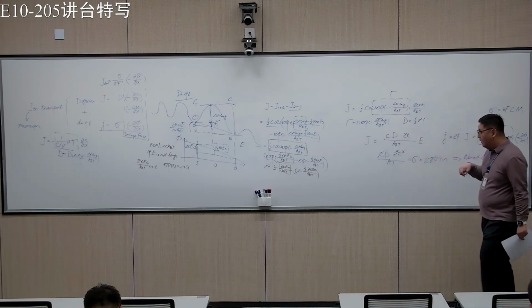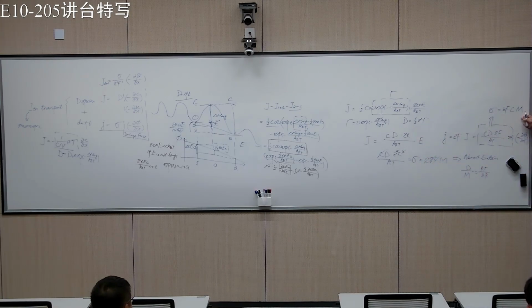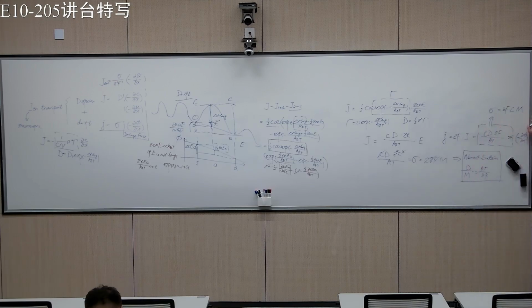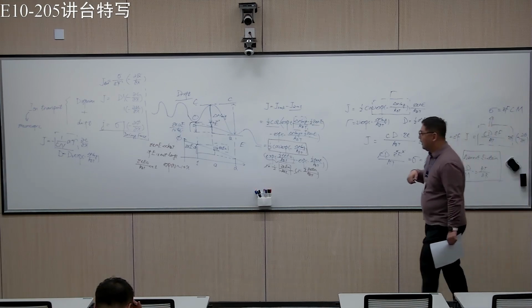In the final part, we say this is conductivity, then we introduce the concept of mobility. You can already see that mobility really comes from the diffusivity. This is really the microscopic origin of the Nernst-Einstein relation, which means that under the electric field, it's still the mobility which matters, giving you the directional flow of your ions or charged particles.